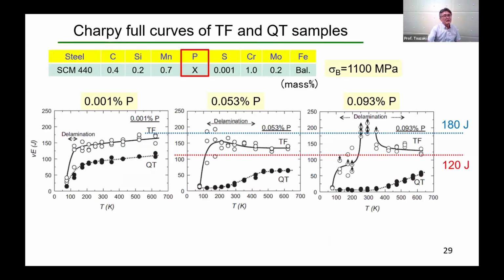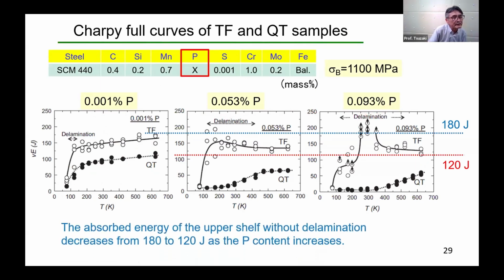Here, Charpy curves of temp-forming TF and quench and tempered QT samples with different P content. 0.001% P, 0.053, and 0.093% P. You can see here the absorbed energy of the upper shelf without delamination decreases from 180 to 120 joule as P content increased to 0.093%. This is the answer to question 1.